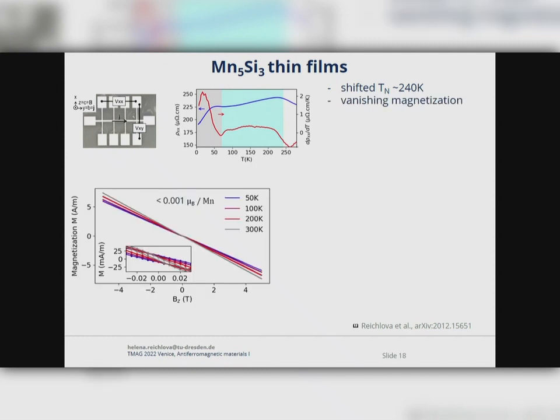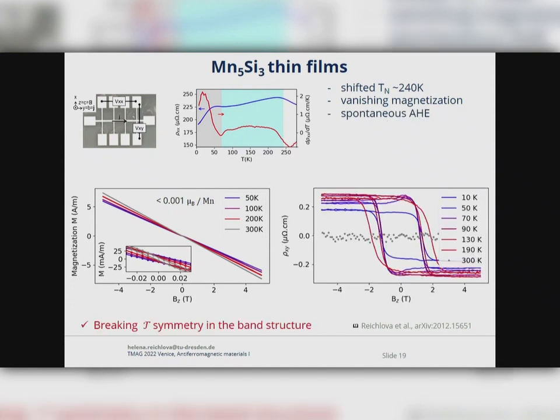And we also started by doing a lot of magnetometry measurements, and we measured at 50 K, 100 K, 200 K, 300 K, and in all these data we could detect only a very weak moment, below our resolution of 0.001 Bohr magneton per manganese. And this is in striking contrast to the magnetotransport data, where we see a robust, clear, anomalous Hall effect, basically in the full temperature range where our films are magnetically ordered. This is then the clear indication that we indeed have time reversal symmetry breaking in the band structure of our collinear material.